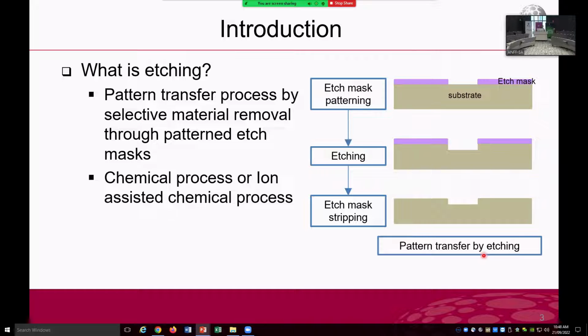Let me use these drawings here. This drawing highlights three steps used in pattern transfer by etching. In the first step, etch mask material is deposited onto your etch target substrate and then patterned like this. In the first step, the protected area and non-protected area in the subsequent etching process are defined. In the etching step, obviously, this patterned substrate having etch mask layer is submerged into an etching environment, and this etchant selectively attacks this etch target material, hopefully without damaging this etch mask pattern.